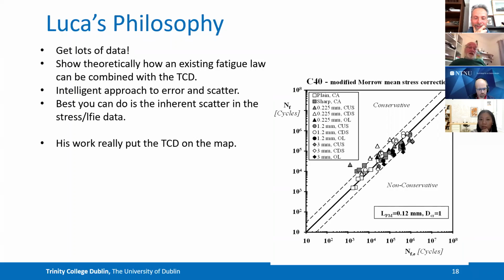And then he looked at all the data that he could find, sometimes his own experiments, sometimes from the literature, and took an intelligent approach to this issue of error and scatter in the data. So we started with this idea of a notional 20% accuracy being good enough. Luca had the idea, which is very simple, but it's simple once you've had it, which is to say, look at the stress life curve, the Wöhler curve. There's always going to be some scatter in the data from the experiments. You can't do any better than that. You can't predict something any better than the inherent scatter that's there.